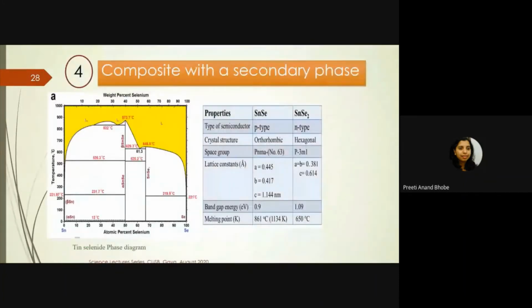So if one looks at the phase diagram, if you try to put one Se atom and one Sn atom and try to make SnSe, then the phase diagram tells us that you need a particular temperature to make this material, but there is a chance that it will go either in a Se deficient or Sn deficient region and form slightly p-type SnSe, or if you take more Se and try to synthesize it, then you will end up getting SnSe2 type of a system as well.